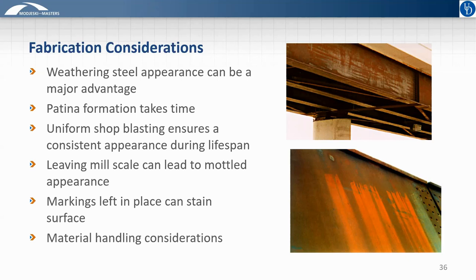A lot of the steel, when it comes from the mill, will have mill scale on it. And it will perform well if you leave the mill scale on, but it does tend to cause the weathering steel to have a very mottled appearance during the early stages of the patina. And it really takes a long time before it becomes more uniform. So the recommendation is to shot blast the girders and remove the mill scale so that you get a more uniform patina formation and much improved aesthetics. Any markings that are often used in steel fabrication that are left on the steel and not removed can stain the surface. That's what's being shown in the bottom picture there. And so that's a consideration as well.